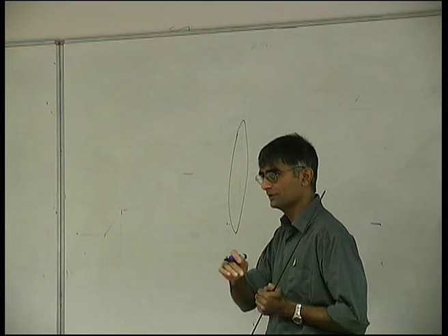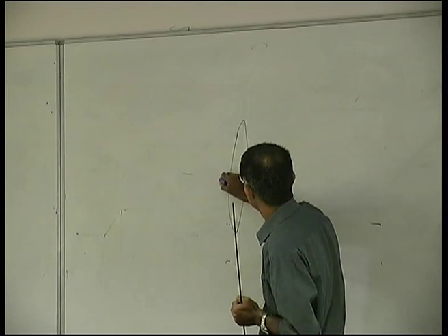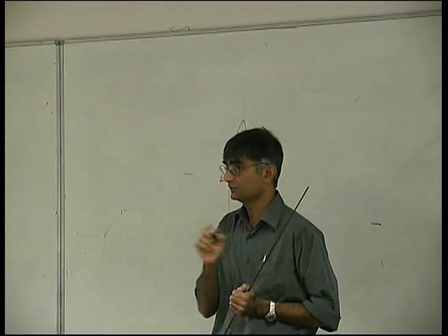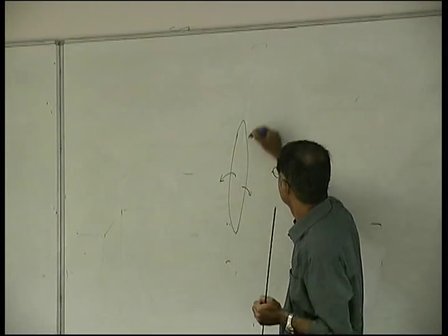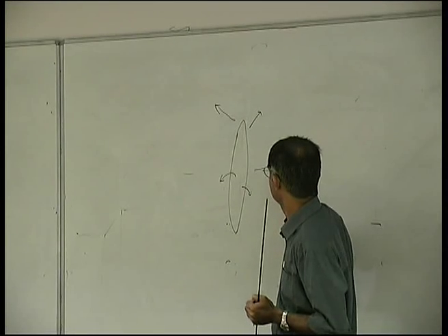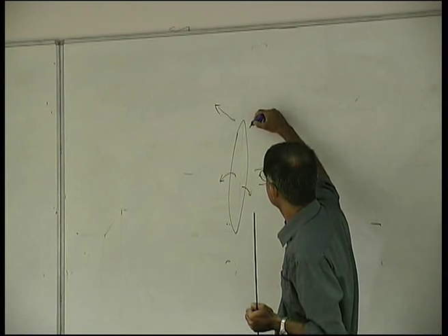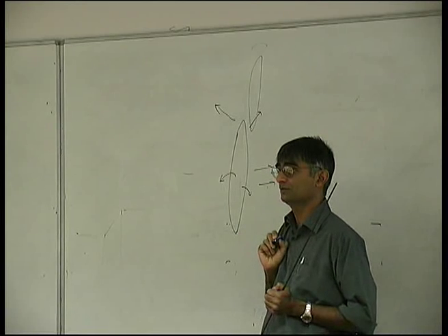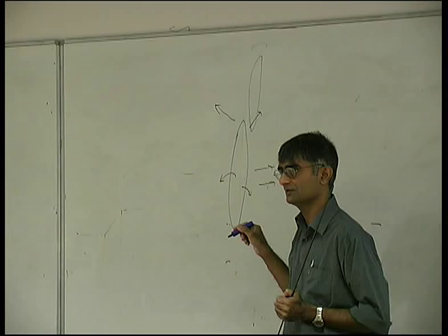So accept that for the moment, it grows without any diffusion. Carbon then escapes from this plate because we are forming bainite at a high temperature compared with martensite. So you establish a carbon diffusion field around here. And diffusion from the tip is much faster than this way, because this is one dimensional and this has more dimensions. So the next platelet to form will be near the tip of that platelet, and that is essentially what determines the spacing between the platelets.